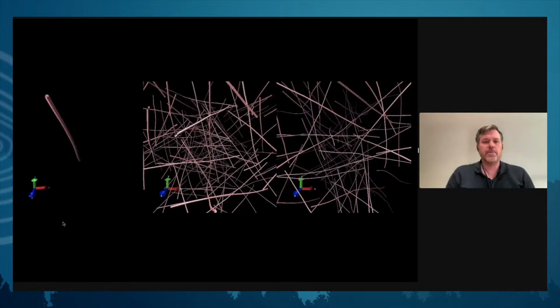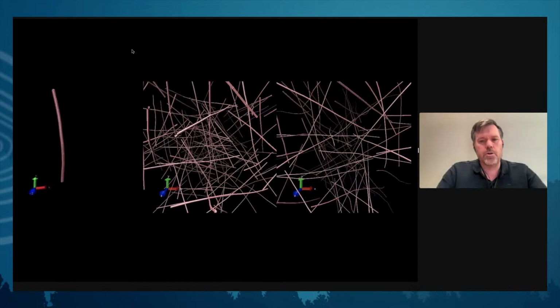And of course, if you start to add more filaments, you will have more things happening. We also start to see that we have interactions that will affect the system. And the last one is the same concentration as the middle movie, but it's a very long fiber with a very high aspect ratio. So this entanglement, the crowdedness of the system, comes out to be very important. And to control this, and this is taken directly from what I've been doing on the paper making side for a long time, trying to understand flocculation, which affects your paper structure and the paper strength performance.